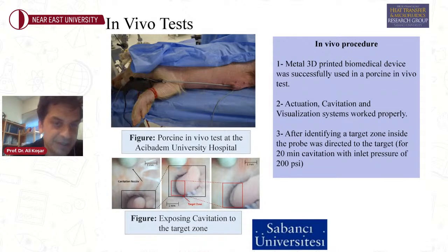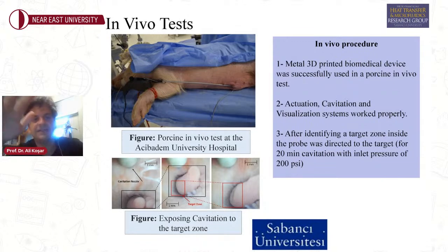for destroying the polyps inside, of course, porcine. And you can see that here within maybe a few minutes, we can destroy the targeted zone. And we can, of course, destroy the whole structure within maybe 15 to 20 minutes with this prototype, a metallic prototype. And we were glad that this metal printed probe could be used in vivo tests, as you can see here. And we also ensured that actuation, cavitation, and visualization systems worked properly.